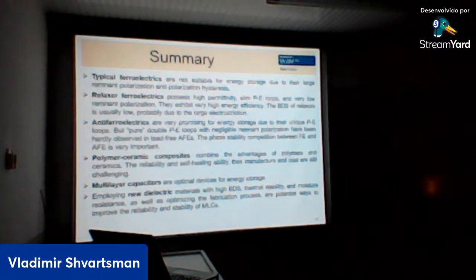Polymer-ceramic composites combine advantages of polymers and ceramics. They are reliable, they have self-healing ability, but their manufacturing costs are still challenging. And when we speak about the optimal geometry, multilayer capacitors will be optimal, since they combine a large active volume of material and the possibility to apply a very high electric field. Employing new dielectric materials with high dielectric breakdown strength, thermal stability, and moisture resistance, as well as optimizing the fabrication process, are potential ways to improve the reliability and stability of such multilayer capacitors.